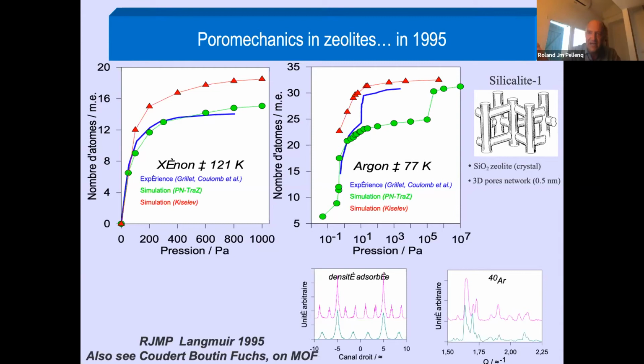It was a change of symmetry of the solid. Clearly the fluid did change the symmetry of the solid. And just to add on that, people in Russia were doing this way before me, they knew that in very small pores you can absorb fluid and it can actually shrink, or depending on the pressure, shrink or even make the thing swell.